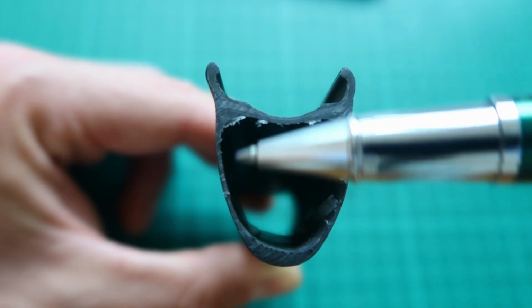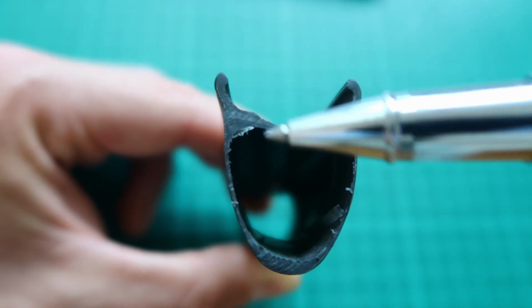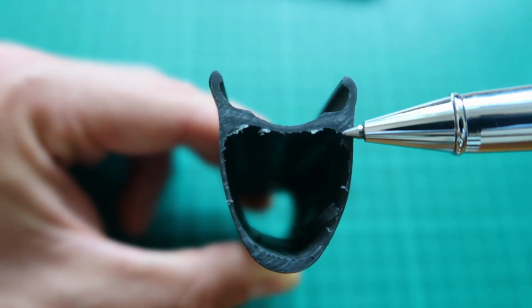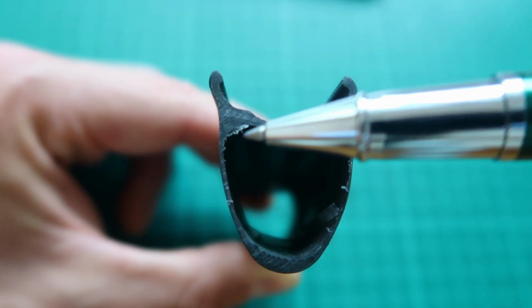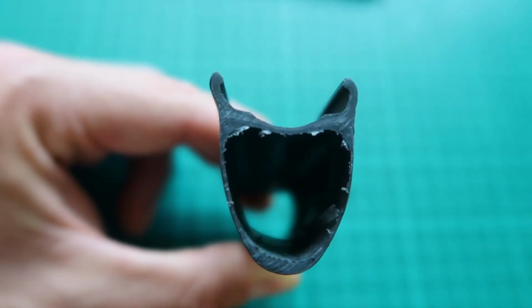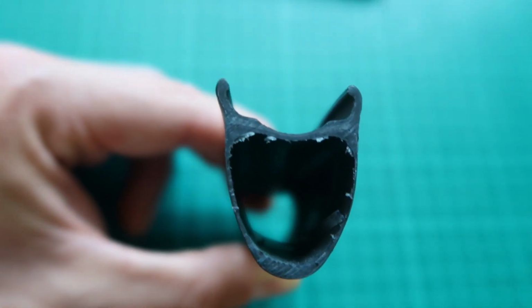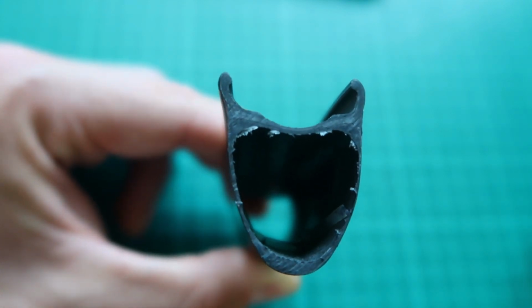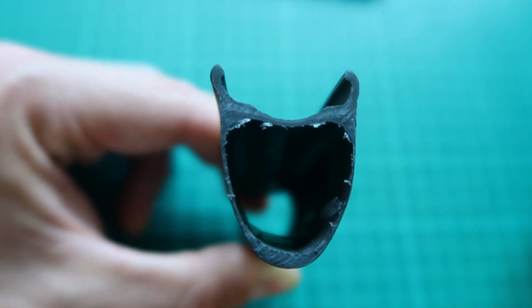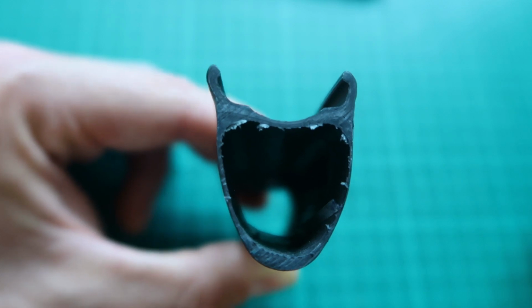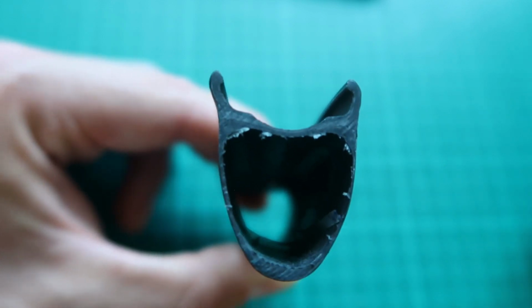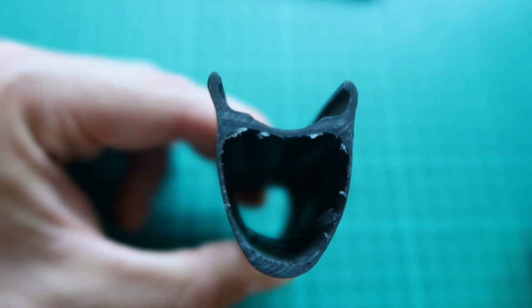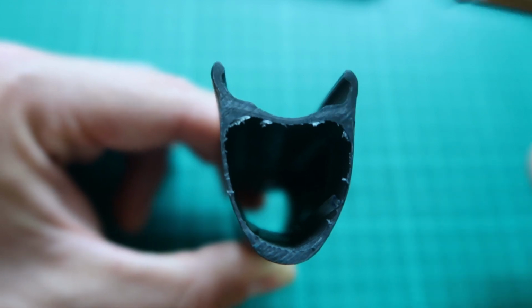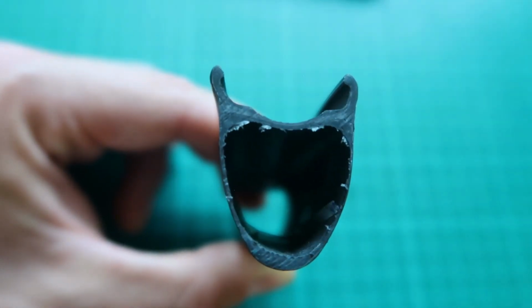I don't actually know what kind of plastic it is, but the inside of it looks okay, and for all the sections I cut, there's no major voids or pores in the laminate, and the laminate is quite well compacted. It's just got too hot. So I'm not dissing the quality of this rim, and actually I don't know, it's an unbranded carbon wheel. I don't know where it was sourced from, but the compaction and the laminate quality is pretty good. It's just got too hot, and that is a problem with carbon clinchers.